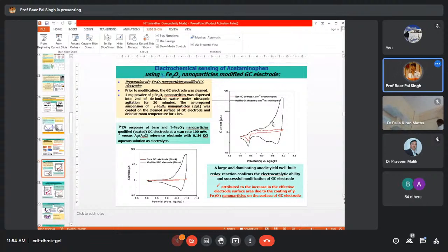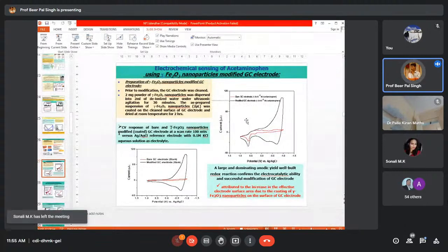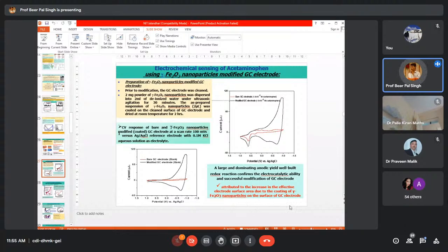Whenever you have acetaminophen, your drug, in the solution, I have taken a concentration of 10 to the power minus 3 mole acetaminophen. In that case, the red one shows the bare glassy carbon electrode behavior of CV measurement, and the black one shows the modified glassy carbon electrode behavior. And you are easily seeing that there is a huge increment in the anodic peak current. That increment in the anodic peak current in the CV measurements really gives an idea that one can sense this particular drug electrochemically by using iron oxide nanoparticles. And that may be just due to the high surface area of the iron oxide nanoparticles which we have synthesized in our research. So that was the idea.